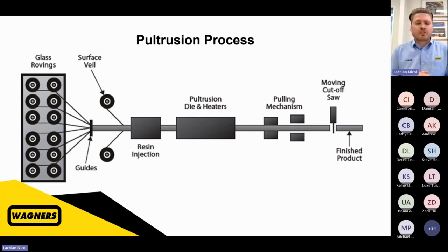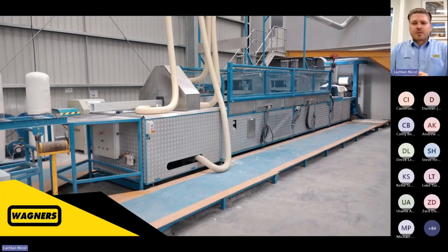Because it's an automated process, we have the ability to run 24 hours a day, 7 days a week without stopping at all. The material is all continuous, so continually injecting resin, continually tying in glass roving, so the process doesn't stop essentially. So we have an inline saw that cuts off all that material to the specific length that we require.